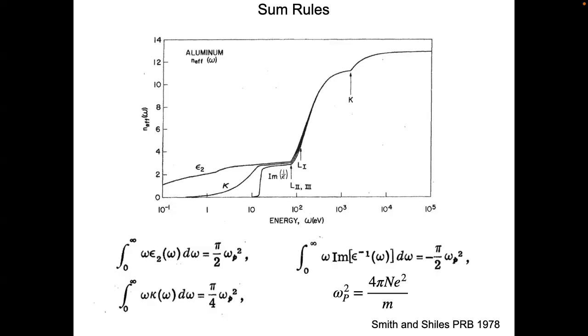They're all different in different ways, but you can see that in all cases they basically equal the same thing on the right, which is a quantity we call the plasma frequency, which is equal to, okay, there are some pi's, the density of charges times the electronic charge squared divided by mass. What mass? Well, if I put in the free electron mass, and then sequentially do this integral out to higher and higher frequencies, that's what you see here.